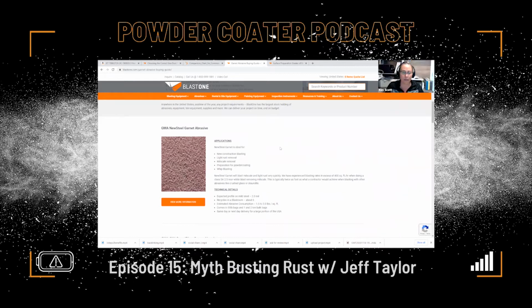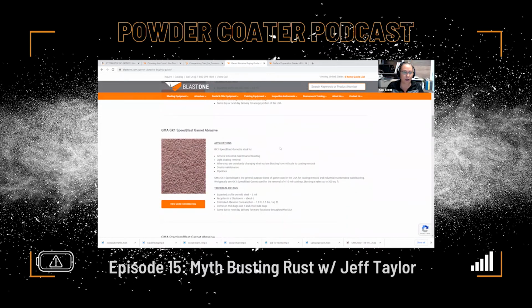That's awesome. Okay. And then now down here, you have G81 SpeedBlast. Yep. So this is a blend of abrasives. It's a blend of your finer abrasive with the coarser abrasive. This is a 30-60 blended with an 80. And this is ideal for general industrial maintenance blasting, light coating removal, where you are constantly changing what you are blasting from mill scale to coating removal, on-site maintenance, and pipeline. So this is a versatile abrasive. It's a little bit more aggressive than your 80 mesh.